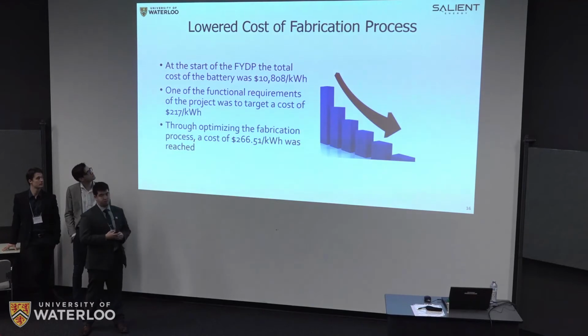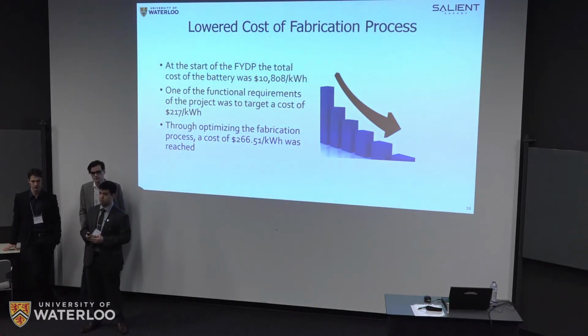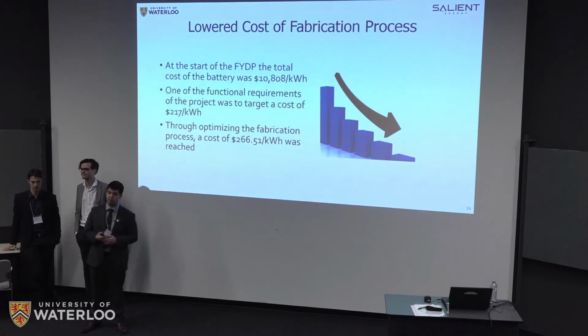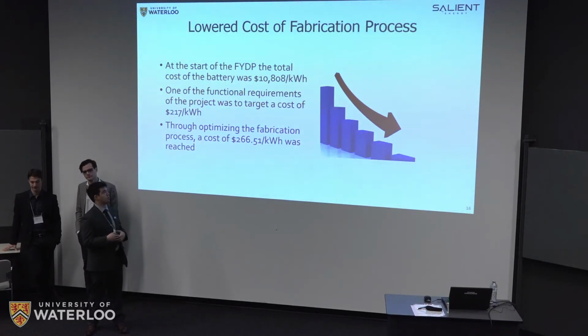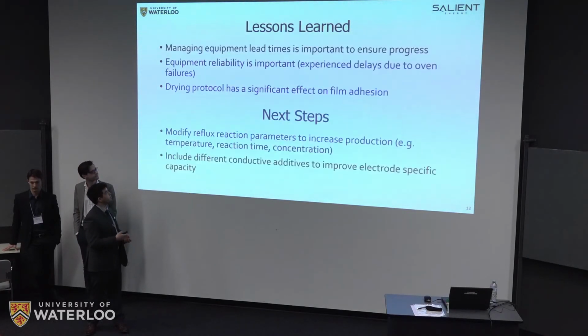In terms of the cost for our fabrication process, we noticed at the beginning of our FYDP that the total cost per kilowatt hour was around $11,000, which was quite high and obviously not at the level that it could be for marketing. So through our group's work in maximizing areal capacity and optimizing the synthesis process, we brought down the cost to around $266, which is close to the target of $217 that we noticed for the bottom of the lithium-ion curve shown on one of the previous slides.